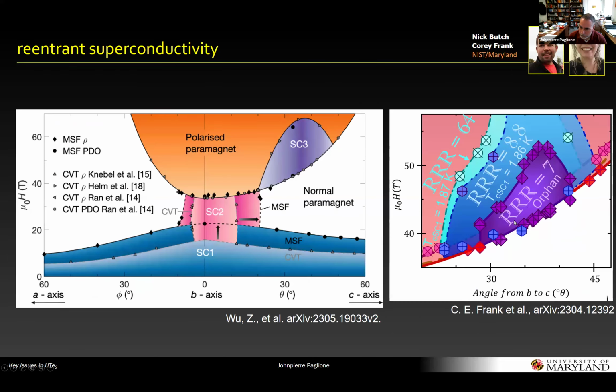So one thing I want to point out, and this is from Nick's group, there's something very unusual here, and this goes back to my comment about the triple R's of samples. Just to point out, this is from Corey's talk. A sample with a triple R of 64 with TC of about 1.9 K is right here, and this is the boundary of the superconductivity in this high field phase. And then there's a triple R of about 9, so that's about a factor of 7 lower with a TC that's about the same and a slightly decreased boundary. But just by looking at these two samples, how could the triple R's be so different? And you still see essentially the same superconductivity.